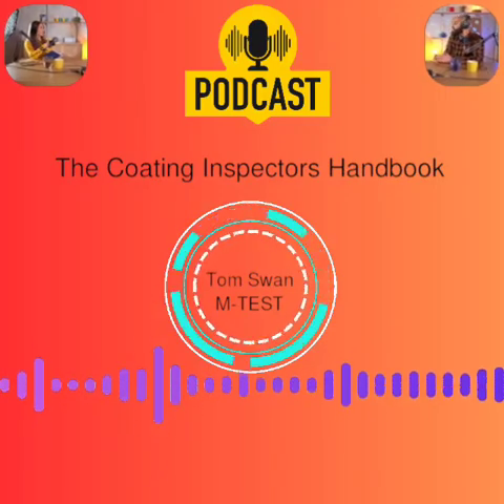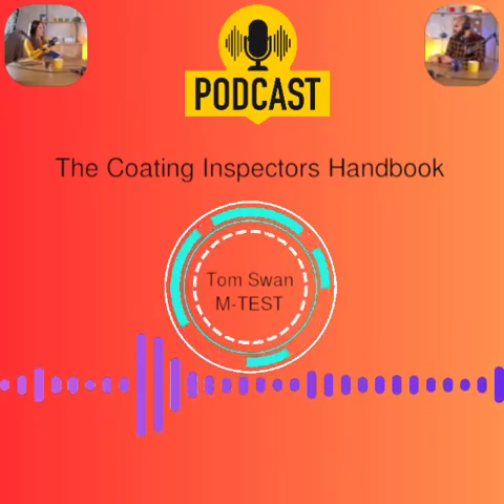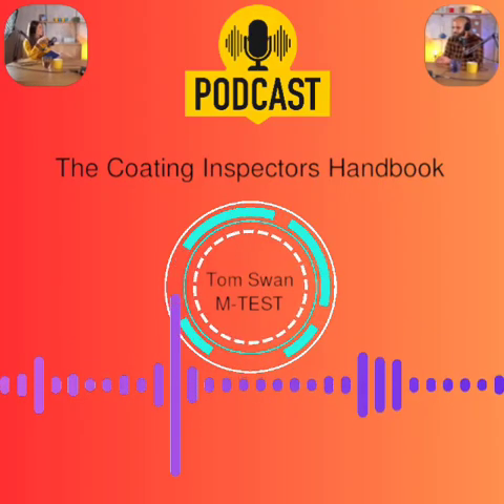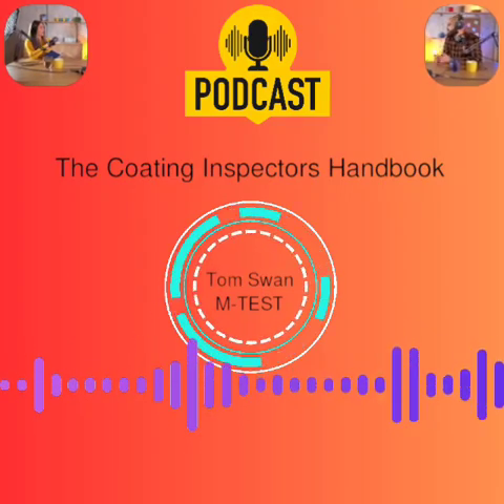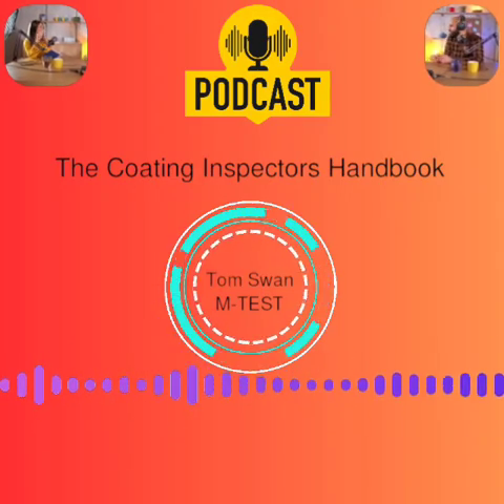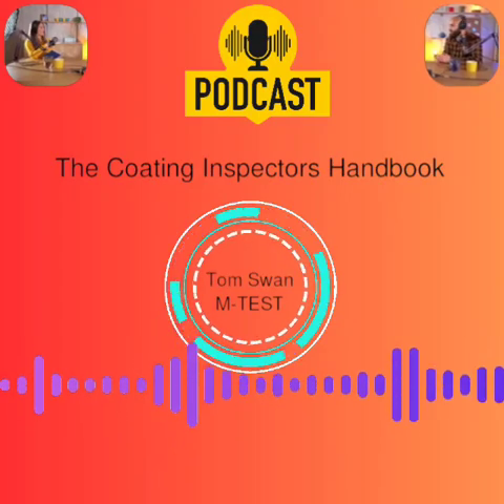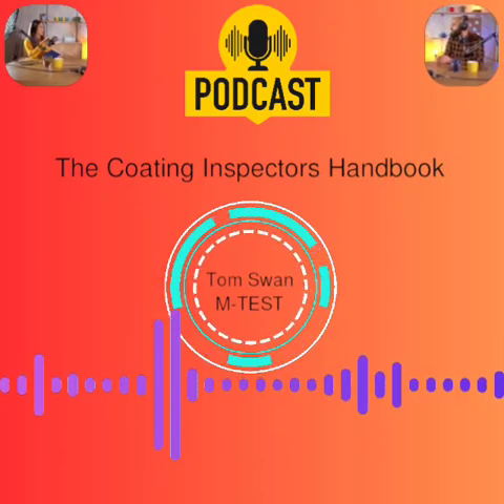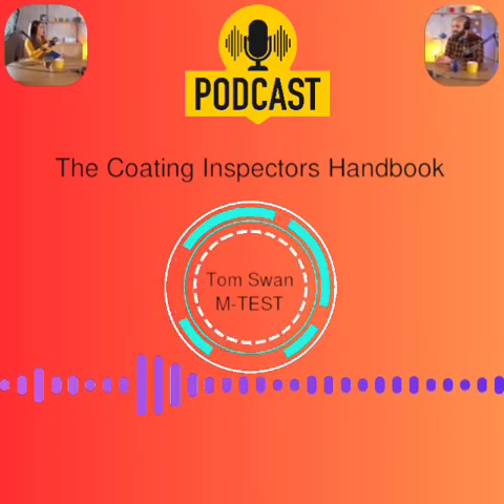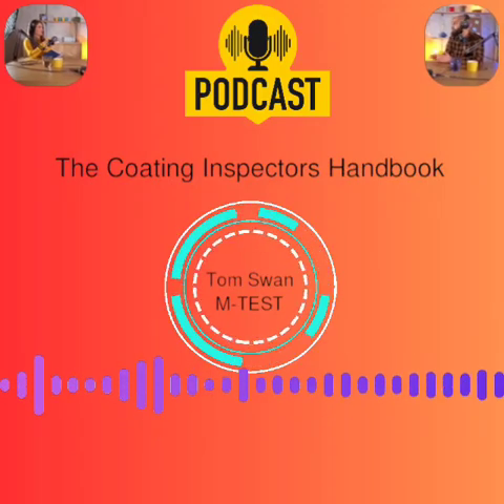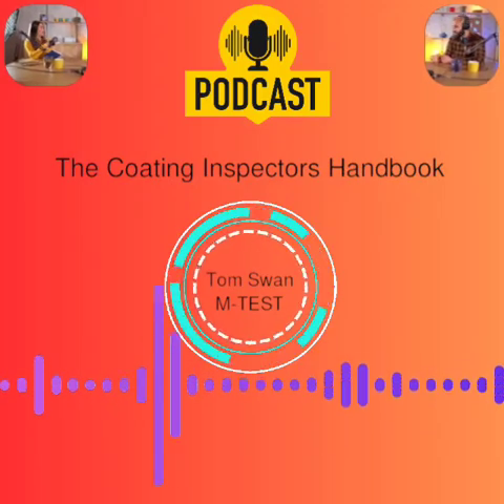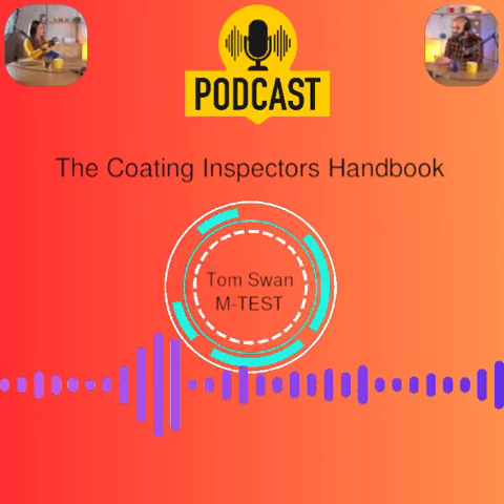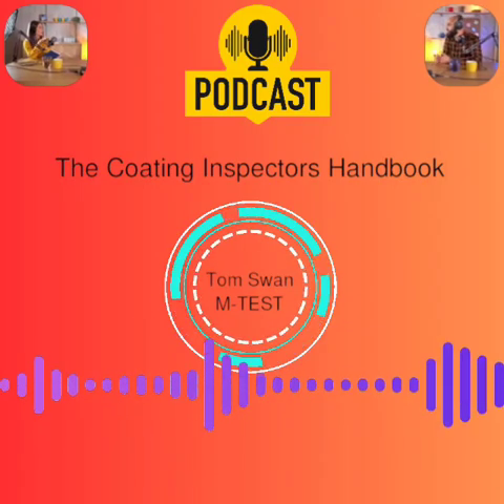Now the PA2 acceptance criteria, this is crucial. Absolutely vital. 2 parts. First, the average of all the spot readings over the whole job must be within the specified DFT range, min and max. Okay, the overall average. But second, and this catches people, each individual spot reading must be within a calculated range. No less than 80% of the specified minimum DFT and no more than 120% of the specified maximum DFT.